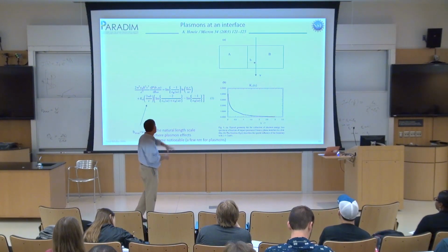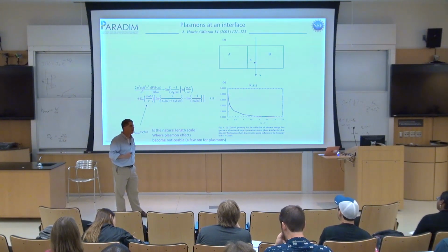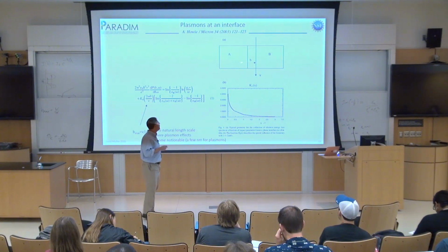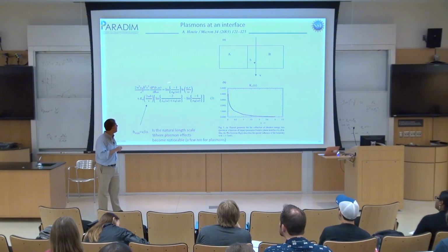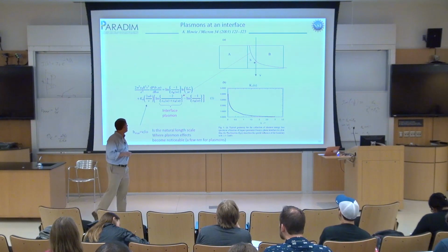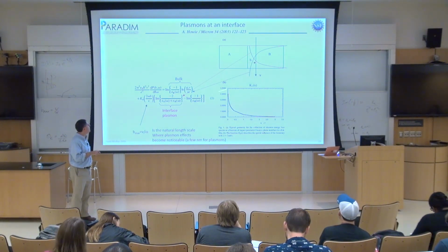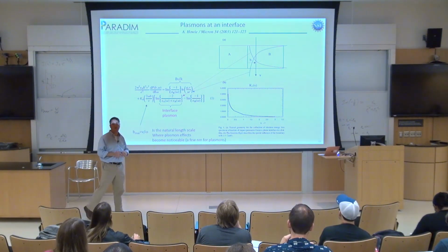If you're trying to do plasmonics, this is a wonderful plasmonics thing. If you're trying to solve a materials problem, you learn nothing about the interface. That's the number one mistake people make, is they think they're going to do optical spectroscopy of the interface. And what this theory is telling you is it's going to tell you about everything but the interface. Okay, so there's my interface plasmon, and it's going to decay exponentially. There's my bulk plasmon over here, and it also drops off at the interface. So the bulk mode is suppressed near the surface of the particle or at an interface.